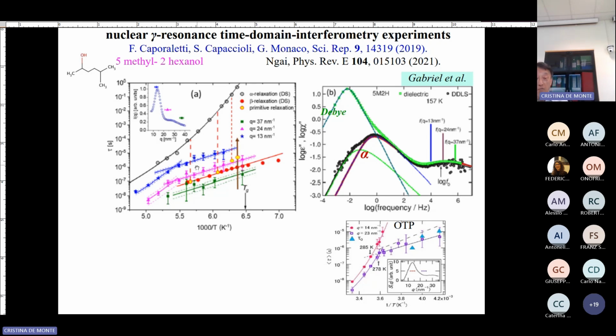And when you find the most local one, and then apply the coupling model, you will see that the data here, the primitive relaxation, the golden circles here, are right there. So this is a very good example of seeing how the coupling model works with Johari-Goldstein in experiment. You see them right there, and you know the Q, and it's a very large Q here, very local. In other words, these are really the simple motions that start the eventual cooperative motion that everybody is focused on. But you have to worry about the beginning. In other words, you think about the origin of this cooperativity. You must understand the beginning, and particularly the relation of these two properties is very specific, very quantitative.